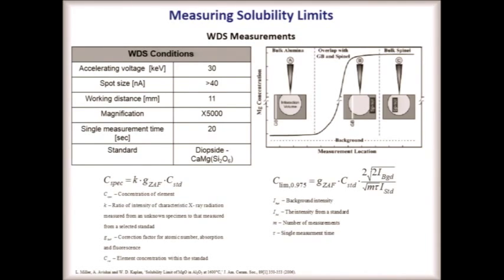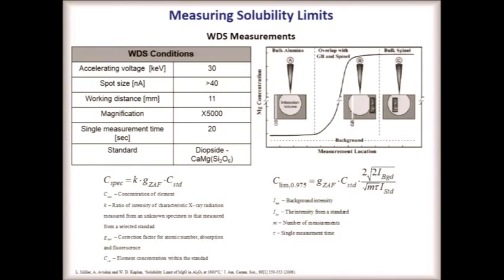The question is, how do we measure just what's happening in the grains and not at the grain boundaries? I remind you all, we obviously can't do a thermal etch because that might alter the chemistry of the surface. And without that, we don't even know where the grain boundaries are. So we're going in blind. And the approach is quite simple, really.